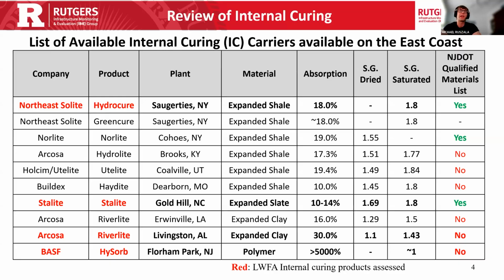We also tested Stalite. It's an expanded slate product from North Carolina. It has a much lower absorption, so you require more of this material to get the proper dosage of the water inside the mix. And then there's the Arcosa product Riverlite, which is an expanded clay product from Alabama. It's a very light material. It has a very high degree of absorption at over 30%. So a lot less is required, but there are some durability considerations that we'll go into as well.